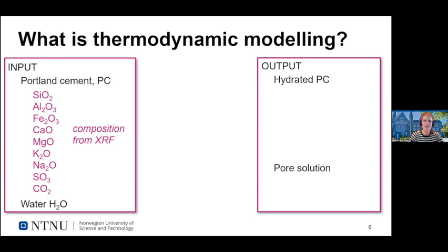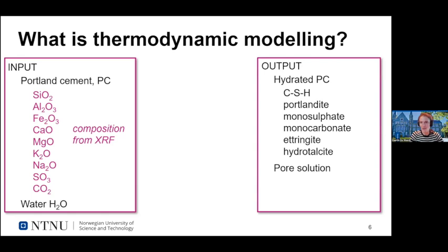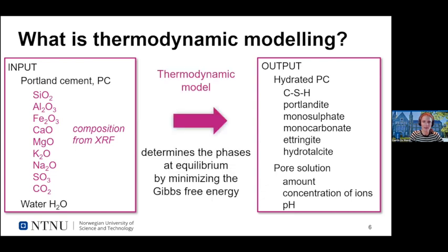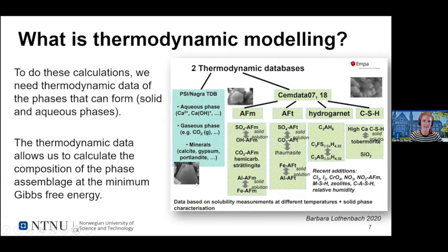Now, what we want to get out is the composition or hydrated assemblage when your cement has reacted. So you want to know how much CSH you have, portlandite, your AFm and AFt phases. In addition, you get out your pore solution. So you know how much of it you have, and you also know the concentration of the ions in it, and thereby also your pH. So this is actually what thermodynamic modeling does. Based on this input, it calculates the output, and it determines the phase assemblage at equilibrium by minimizing the Gibbs free energy. In order to do these calculations, we need thermodynamic data of the phases that form and also of the aqueous phases. The thermodynamic data allows us then to calculate which composition of these phases will give us the minimum Gibbs free energy.